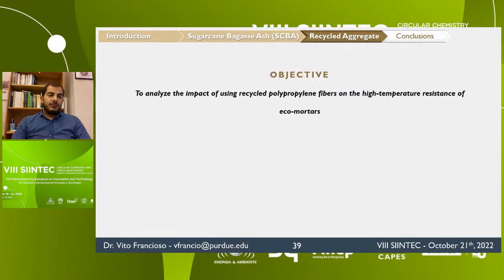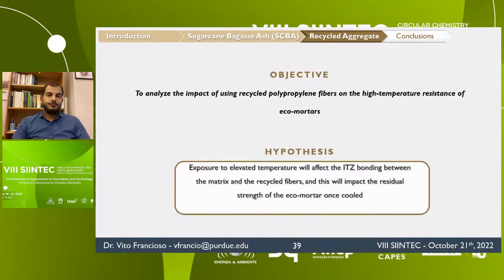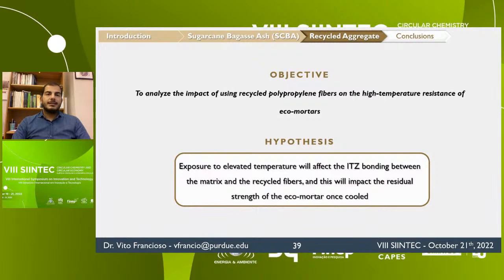So the objective of this study was to analyze the impact of using recycled polypropylene fibers on the high temperature resistance of eco-mortars. My hypothesis is that the exposure to elevated temperature will affect the interfacial transition zone bonding between the matrix and the recycled fibers, and this will impact the residual strength of the eco-mortars once they are cooled down.